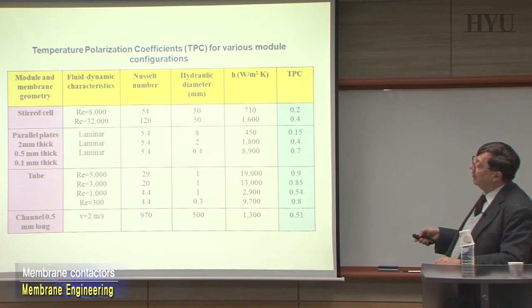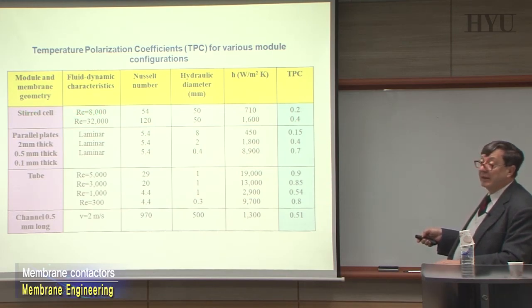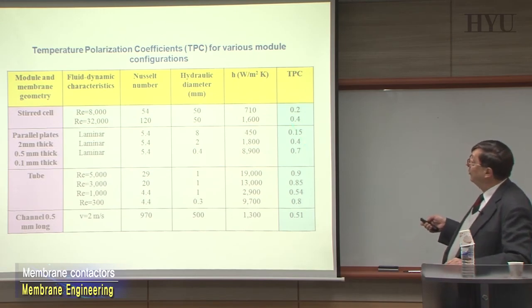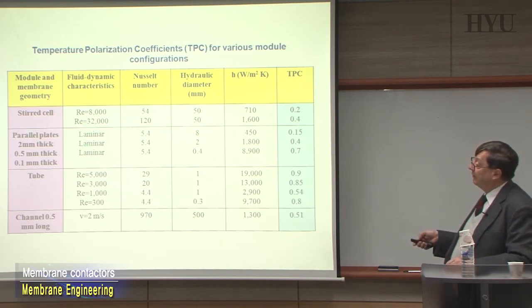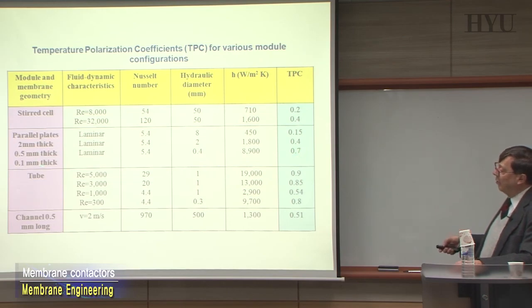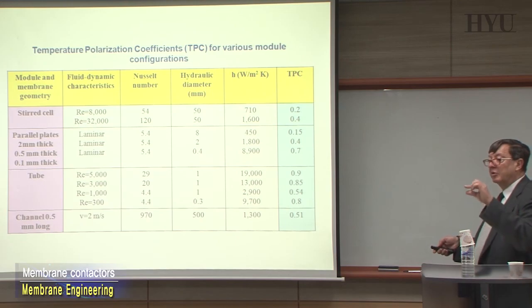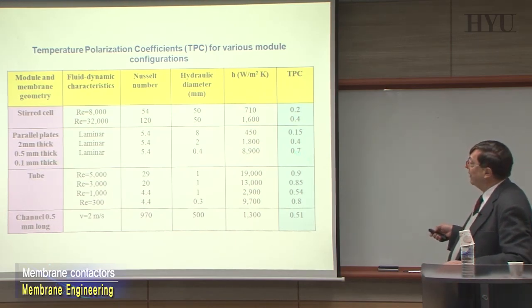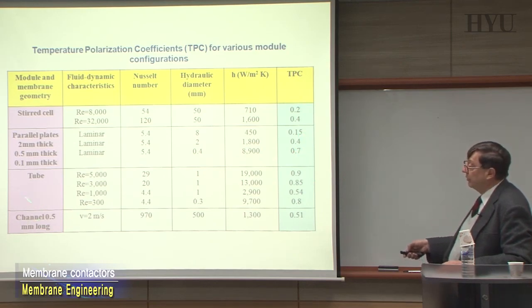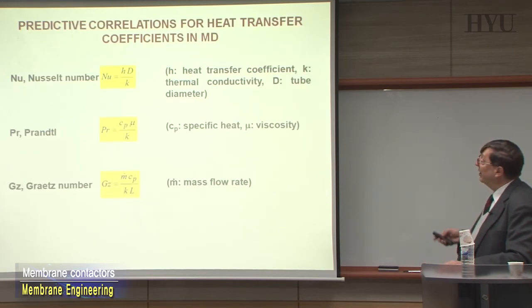And this is a different condition. In case you see here, if you are having a stirred cell with Reynolds 8000, you have a 0.2. When you go to Reynolds 32,000, high mixing, etc., you improve to 0.4. Still not ideal, but that is the effect of just stirring. Here you have a laminar flow, and if you change the thickness, again here 0.15, 0.4, 0.7. That means when you are going with relatively smaller thickness of your membranes, you can improve the concentration polarization control, still not approaching the ideal value, but much better than 0.15, and so on. That is, the different level of Reynolds number can have an effect, and that is the typical case.